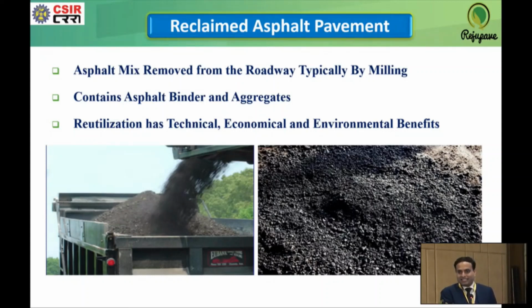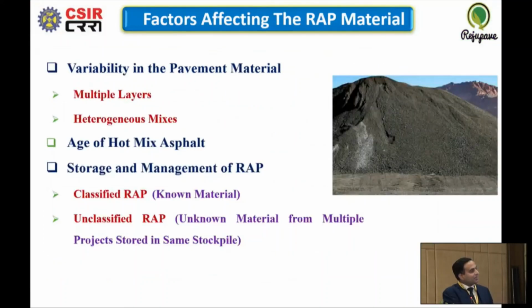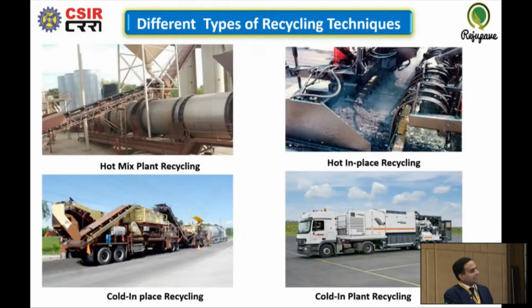It is all natural aggregate. So what we did, we reutilized this. We classified it into coarse and fine RAP by segregating it into minus 10 mm and plus 10 mm, and with the help of it, we devised the mechanism to put it into the hot mix plant and get it reutilized.